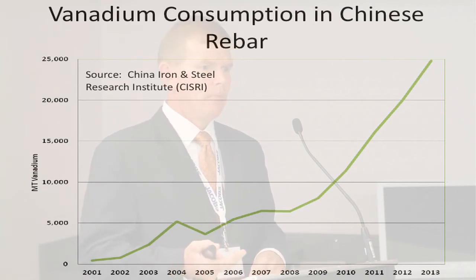Now, you can do that, but there's implications. And if you look at it from a metallurgical standpoint, niobium, titanium, and vanadium, they all strengthen steel, but they do it through very different physical metallurgical processes. So you can get to the same yield strength, but there's implications in terms of processing, in terms of how the steel is going to perform in the field. And there's always a best way to make a certain type of steel. And sometimes it's vanadium, sometimes it's niobium, sometimes it's titanium. There's always metallurgically a best way. But when the economic factors get out of whack to a big enough extent, what you see is people forcing that square peg into the round hole. So in this period, a lot of these rebar producers moved to niobium plus titanium.